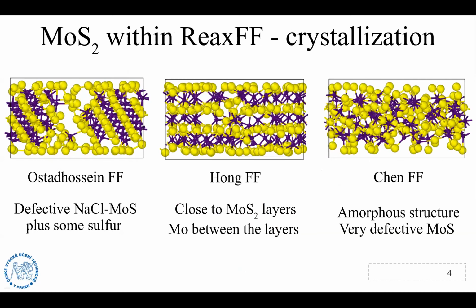And what we get from the state-of-the-art force fields is not really satisfying. One of those produces a completely wrong crystalline phase. Another produces something that very much resembles the correct result. However, it's not really the thing that is necessary. Another one produces an amorphous structure. And again, given experimental and previous simulations, we would expect the MoS2 to actually crystallize in a very constrained environment. So we figured there is no really satisfying ReaxFF parameterization.